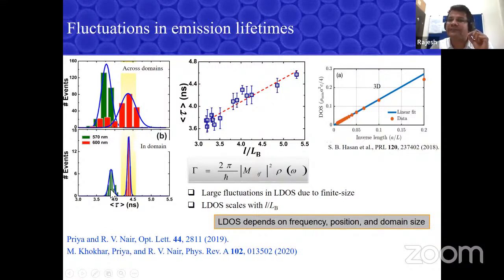Then we looked at how this lifetime varies across the sample. And what we have is the lifetime as a function of the thickness of the sample. L is the thickness and L_B is a normalized parameter of the sample. So it has a little bit of a linear scaling in the system. So the LDOS, the local density of states in a band gap, scales linearly with the thickness of your sample. When we did this experiment, there was a theoretical calculation published in a PRL, which shows that in a photonic band gap, the density of states scales with the system size. And that's precisely what we measured in our experiments. The only difference is that here it is a 3-dimensional band gap, and we are only looking at one direction. But it actually gives a signature of the system. So the conventional book says LDOS depends on frequency and position, but this result shows that it also depends on your system size. We have published a couple of papers recently on that, so you can look into them if somebody is interested in a more detailed, elaborate explanation and experiments.